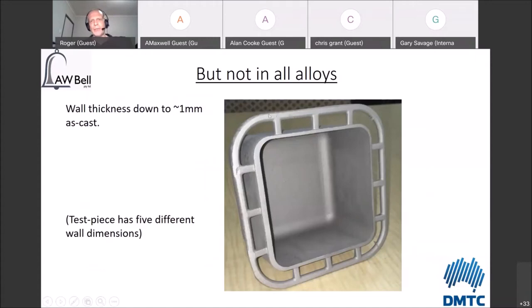The frame around the outside of it that you see here is there purely for structural purposes. It's not there to feed it. Basically, when you are casting down around 1 millimeter in investment castings, you have to be very careful that you constrain things so they don't move around too much, or when you try to cut stuff off it starts to bend and move all over the place, and then you have a different problem to deal with. So this ring is only there to stiffen up the outside of it to hold it all in position while we cast it.